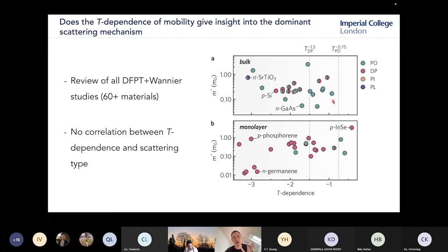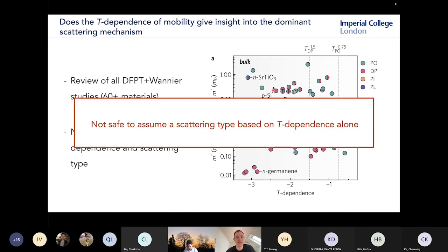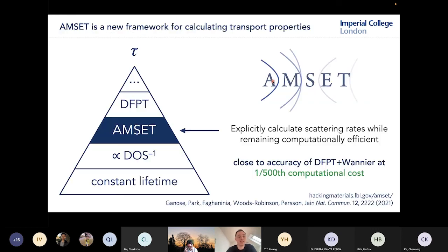And so after I made this, this was the first indication that it's not safe to assume a scattering type based only on the temperature dependence. There's something else going on here. And so to investigate this further, I turned to AMSET and did some calculations using the AMSET package.